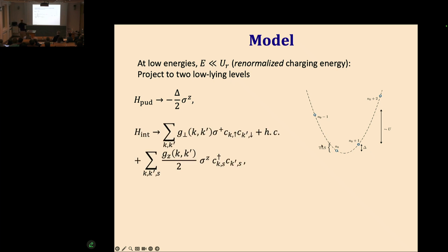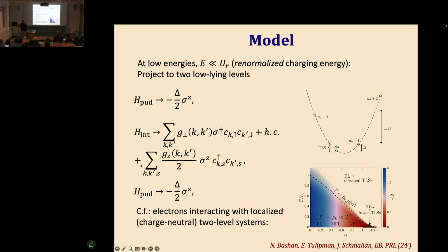And we can write the same Hamiltonian just in terms of Pauli matrices, where this Pauli matrix sigma z, being +1 or -1, corresponds to the two lowest energy levels of our superconducting islands, corresponding to n and n+1 Cooper pairs. You can ask, well, what's special actually about superconducting puddles? We can have two-level systems in a normal metal that have a completely non-superconducting origin, some kind of localized level that's interacting with electrons. We've actually studied a similar problem, with non-superconducting two-level systems and the scattering of electrons from these two-level systems.